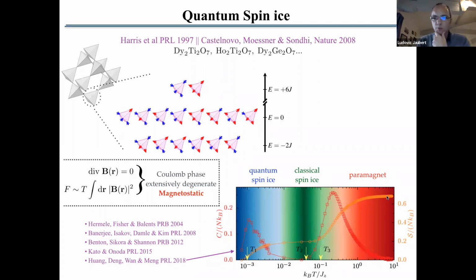When you are at high temperature, the entropy is R log 2 because you have a quantum spin S equal 1/2, so that's simply R log 2. Then as you decrease temperature, you have the first bump of classical spin ice, and then you enter into the classical spin ice regime in green here with a plateau of the entropy, which corresponds to the plateau of classical spin ice. That's this residual entropy I was talking about about this ground state.